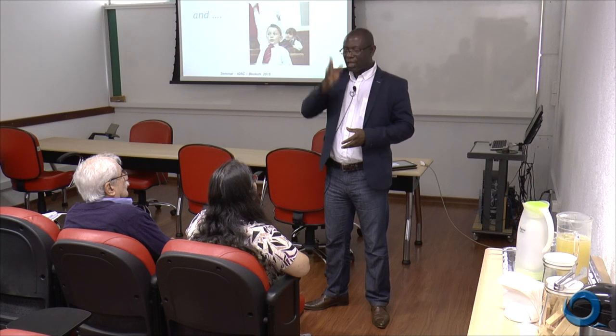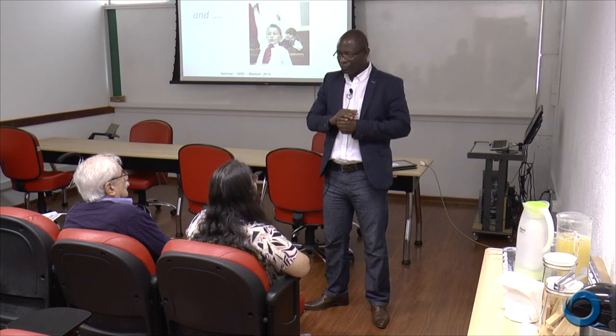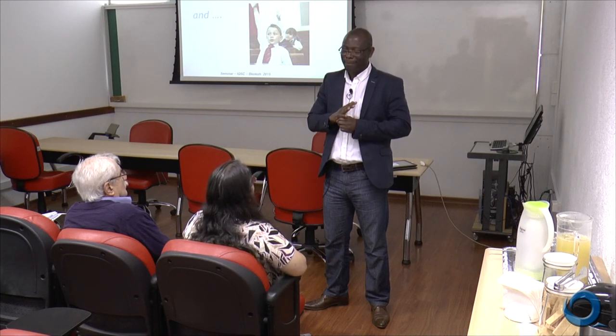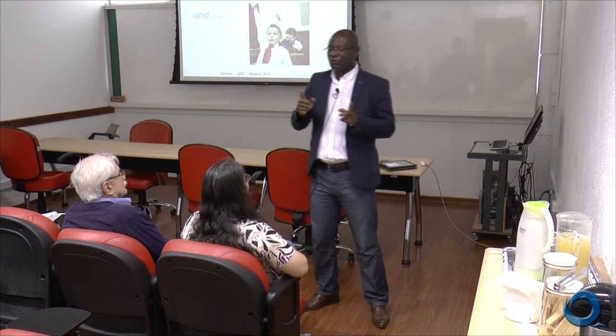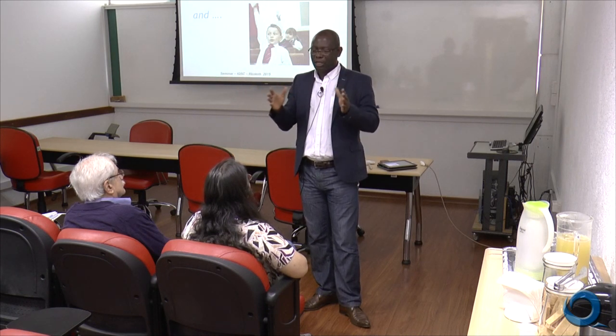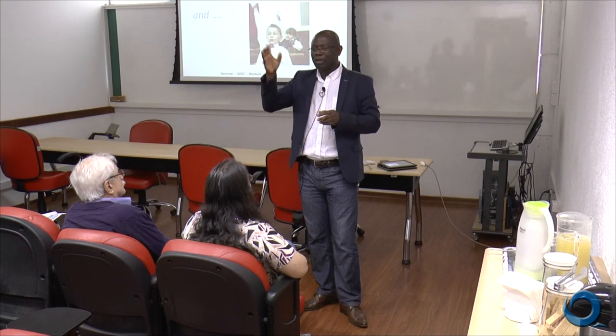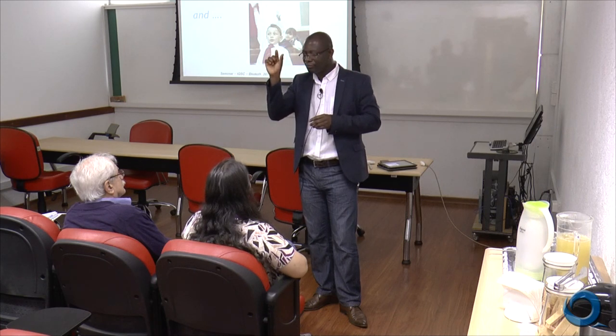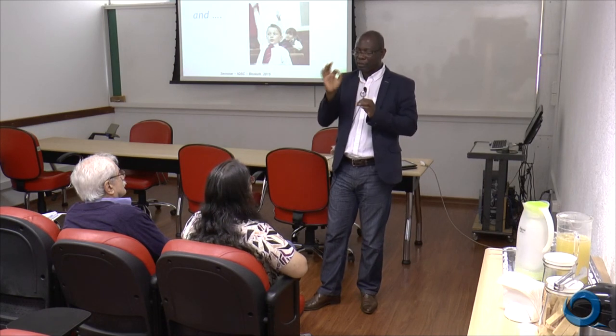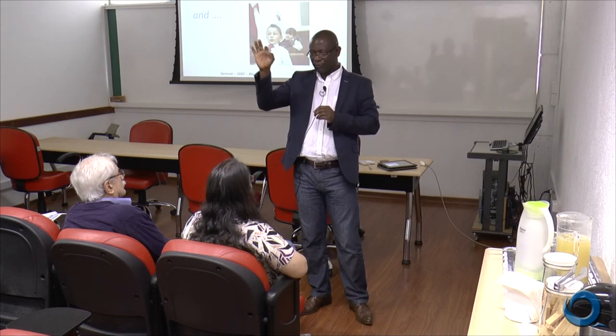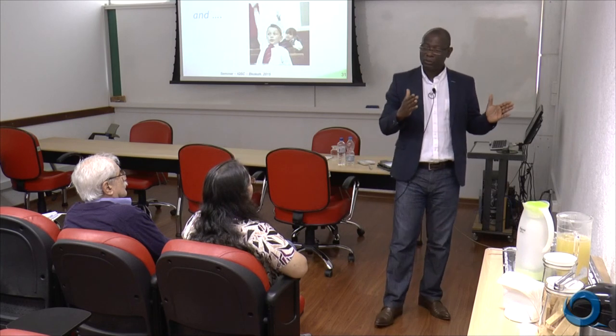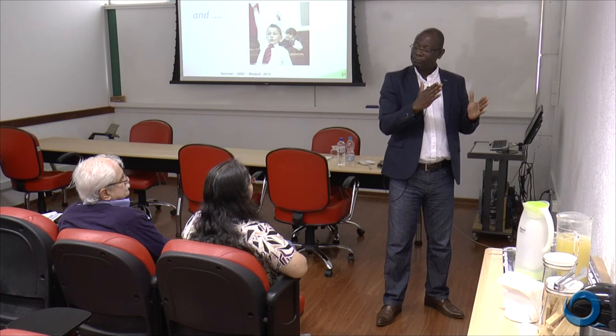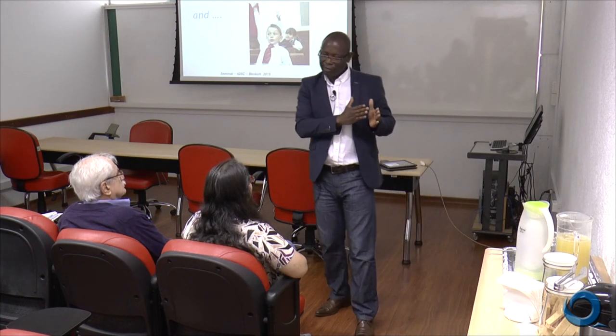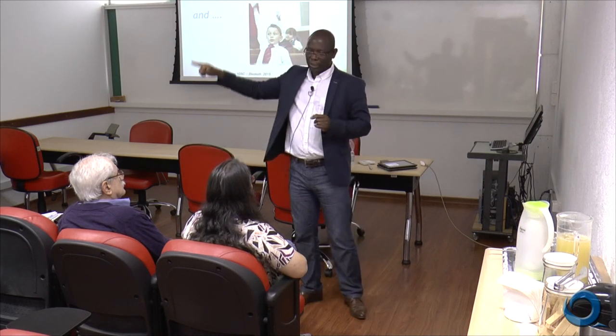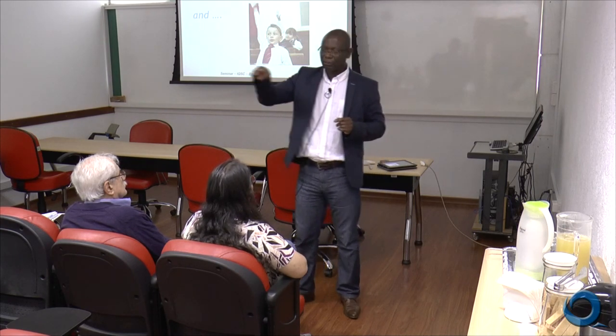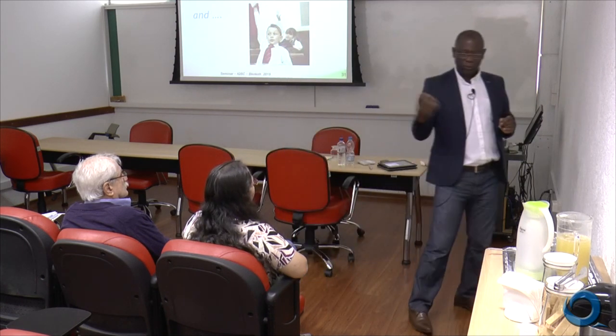Usually, a lot of students start at 0.05. No, it's not good. You know why? Because the standby potential of your potentiostat gives you some value, maybe at 0.5, so you have to look at this value, and with your potentiostat you can take the free potential. If you start at lower potential, you force your potentiostat to start at 0.05. So if you take this value, you record, and after you start at 0.05, and you continue. This is more convenient for your system.